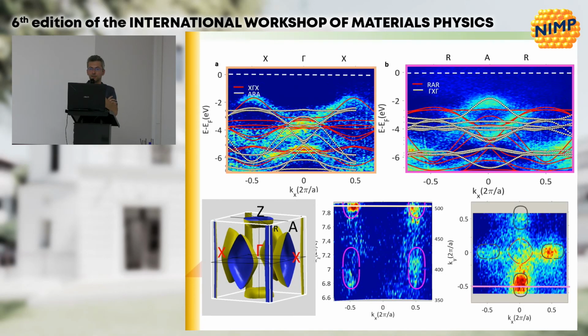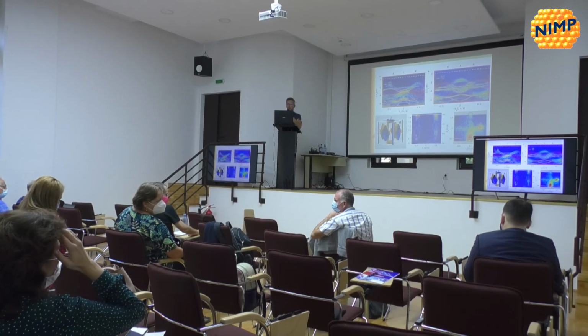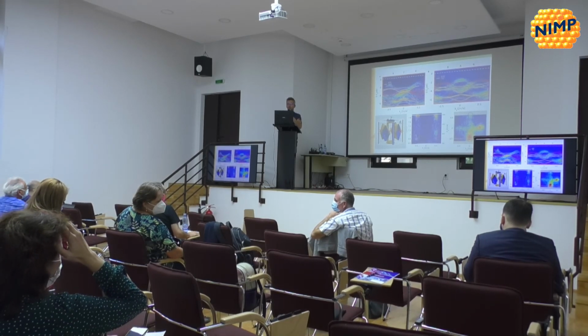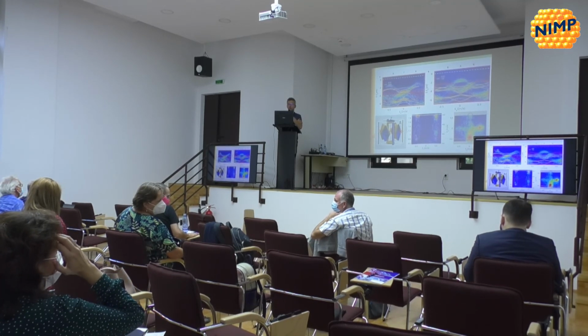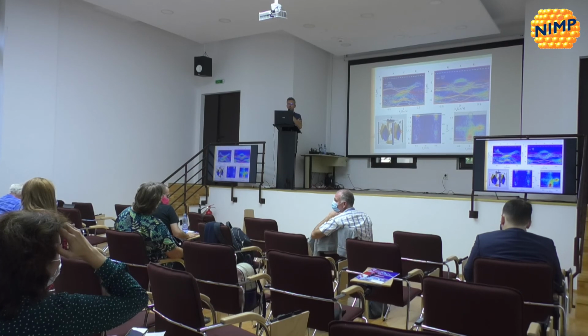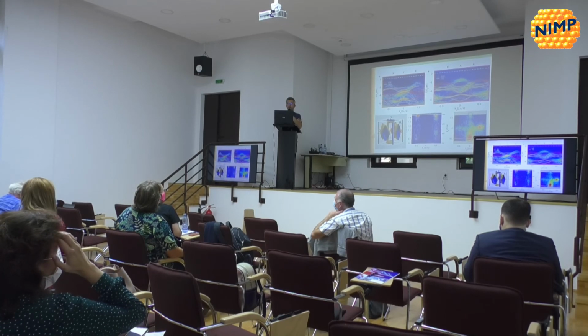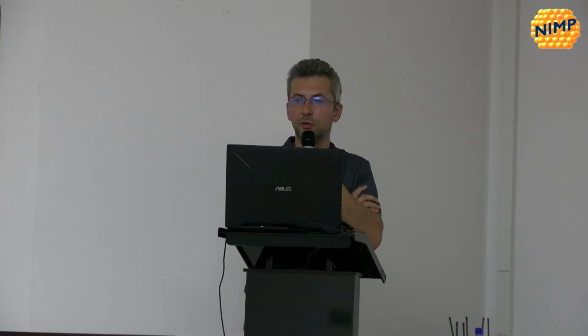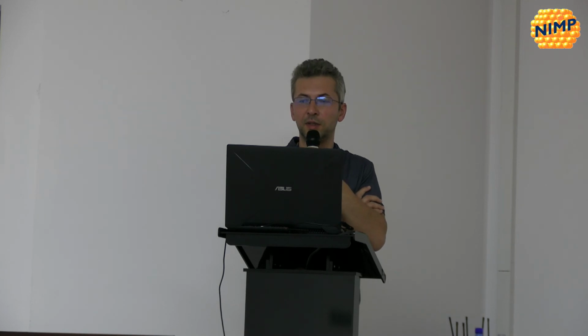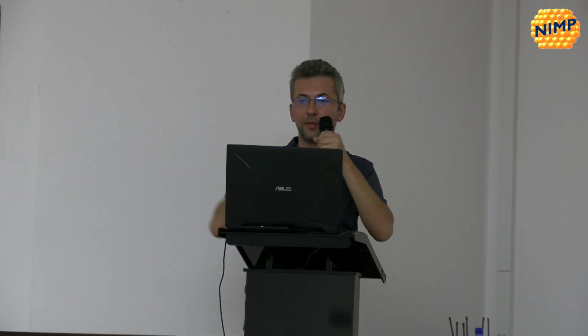Okay. Another question: have you seen any effect of charge transfer as a function of polarization from the LSMO electrode into the PZT, which could, for example, dope the PZT one way or the other and therefore shift the bands? Actually, we had in mind to look at that. We realized that the thickness of the PZT is too large to see anything from LSMO. So basically, we don't see the bottom interface. We see just the surface, probing maybe in the range of 2-3 nanometers out of these 5 nanometers, the entire thickness.